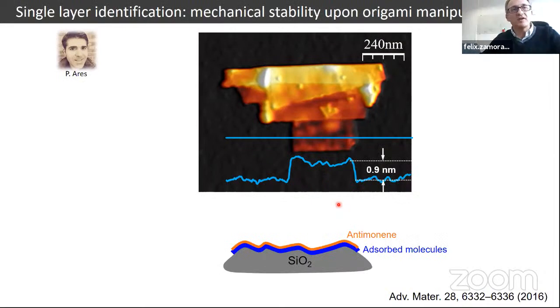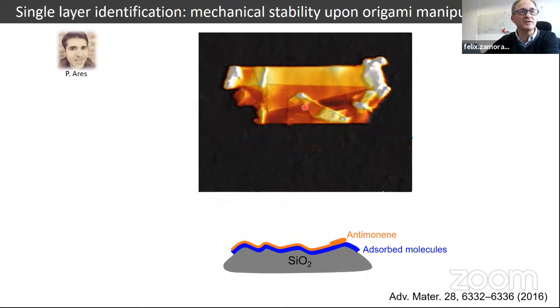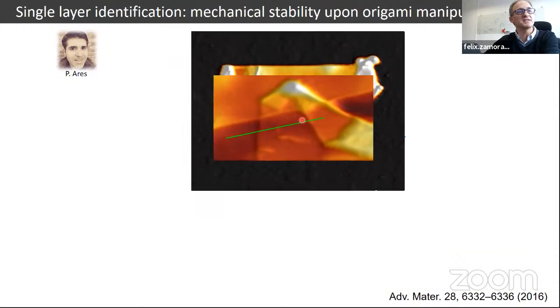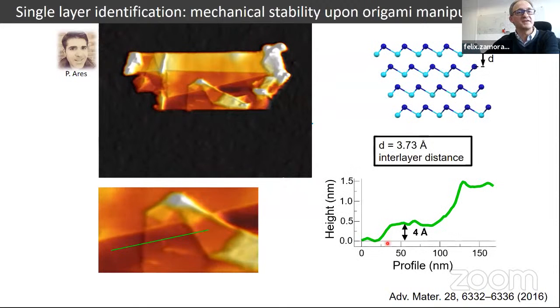And this is a very interesting experiment. When we were looking for small layers in this process, we found really small quantities of layers having a really small thickness, as small as 0.9 nanometers. So this should correspond with a single layer, of course. But in order to demonstrate that we have a single layer, Pablo did a very difficult experiment, which is based on folding with the AFM tip. He folded this part of the layer on top of the other bigger layers, and then he was able to remeasure the height, and what he observed is a height of 4 angstrom. As you can see here, this height profile corresponds nicely with the interlayer distance in the beta antimony crystals, confirming that this part of the layer corresponds to just one single layer.